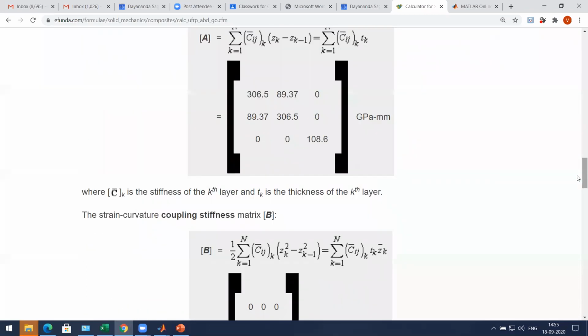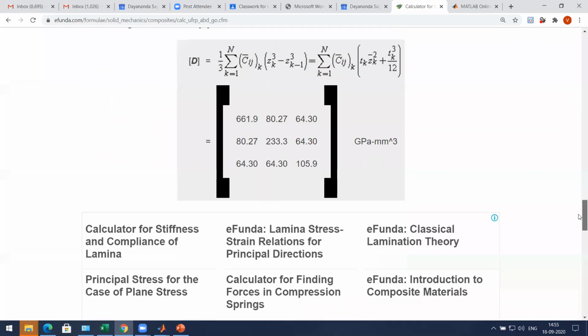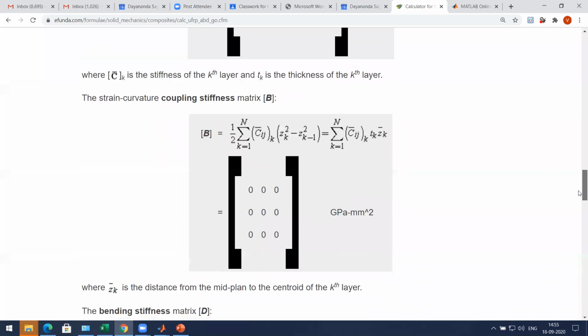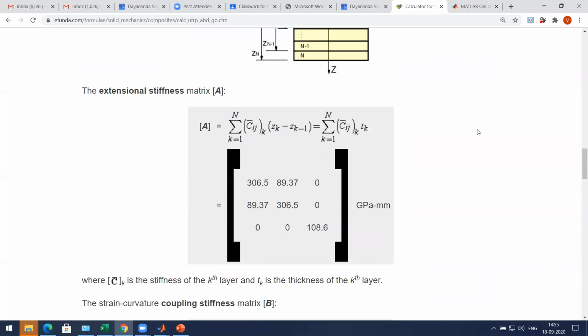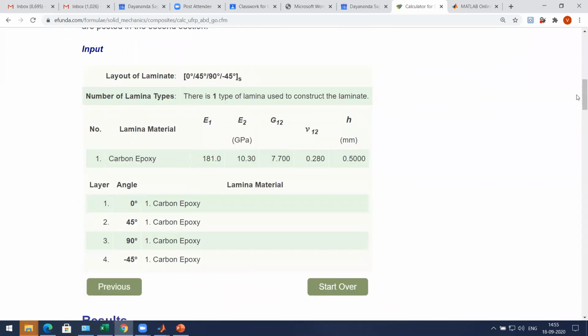That is the total laminate, and you will still have the A matrix like a quasi-isotropic. That's why we call it quasi-isotropic. The B matrix is like isotropic since all the elements are 0, and the only problem is with the D matrix. So it is almost like isotropic, but you can't call it isotropic. Mostly people look for quasi-isotropic whenever they want to somewhat get the metal behavior. So for isotropic behavior, they go for a quasi-isotropic laminate.